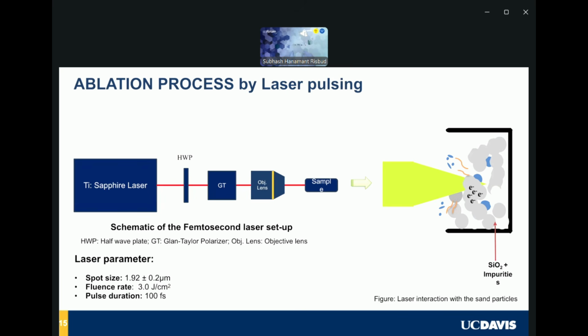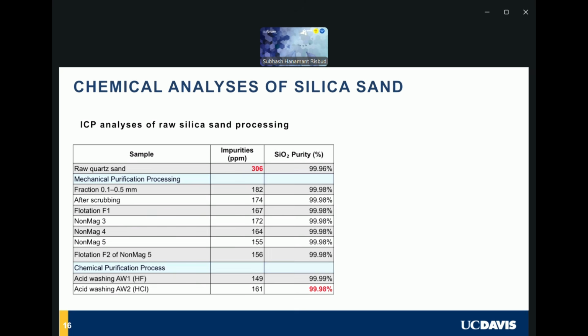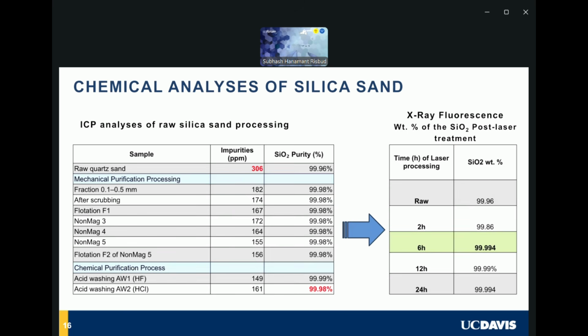So the way this system works is we set up a femtosecond laser, and then all of you familiar with this laser know that the pulse duration is only about 100 femtoseconds. And then the sample is this way, the laser beam hits it, and then it goes on, and then material ejection occurs, and here's the analysis. So if you do chemical analysis of chemically purified acid wash materials, you get something like 99.98 at best, but it's a very tedious process.